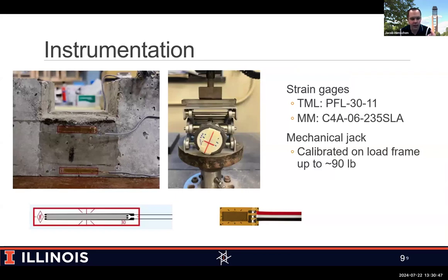With the specimens, you can see that we created some with notches, and it was basically a blank that we would insert into the molds during the casting process that was later removed. The specimens after casting, we use surface mounted strain gauges with them.